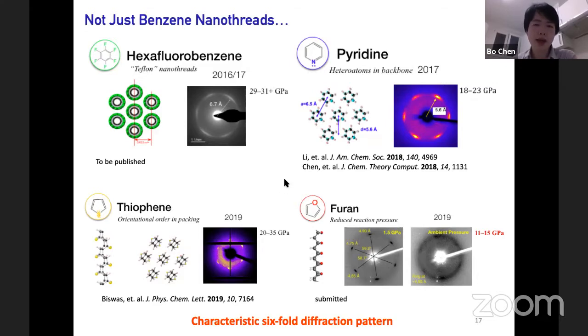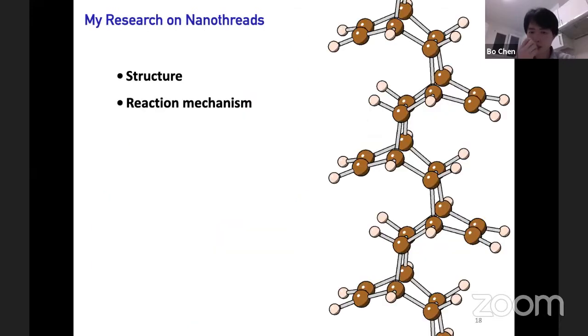And here I want to point out that if we start with rings with heteroatoms, the heteroatoms will end up in the backbone of the nanothread. That is kind of a neat way to dope the nanothread, if you will. And it's a much better way to dope nanothread if you compare, for example, doping nanotubes, which is very difficult. You cannot get many of the heteroatoms in the nanotube. So that's sort of a long introduction.